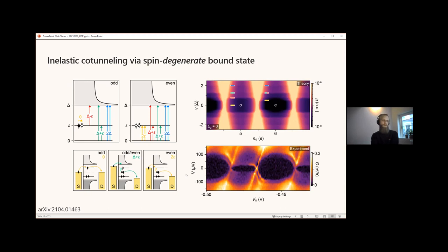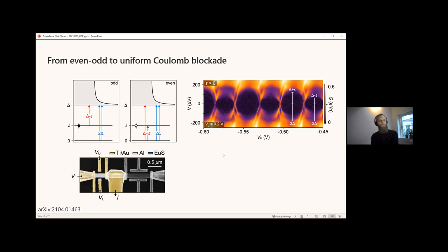Good. The results that I've shown so far are from a single island, but we also reproduce them in other devices. Here is an example from a second wire, second island, showing even-odd Coulomb blockade. Now, if we compare it to the model, we can assign the energy of these Coulomb features to specific excitation transport processes, and extract the induced gap and the subgap state energy.